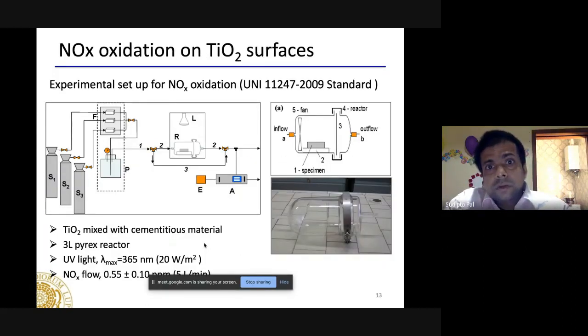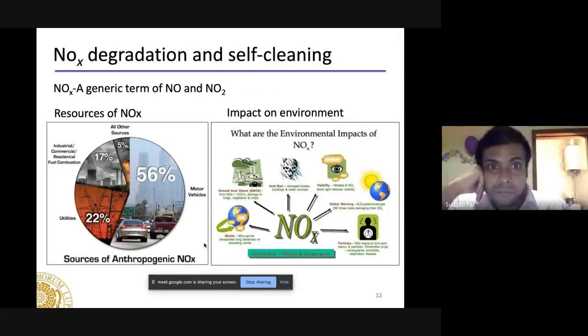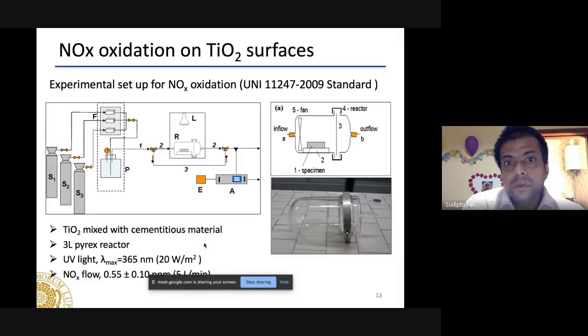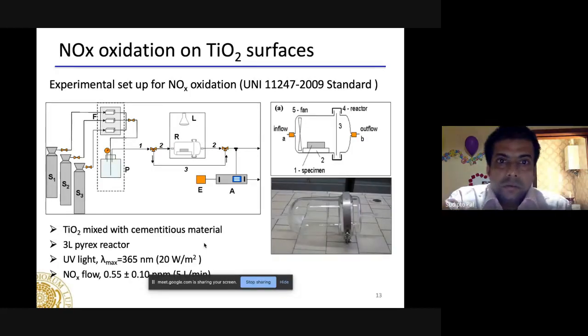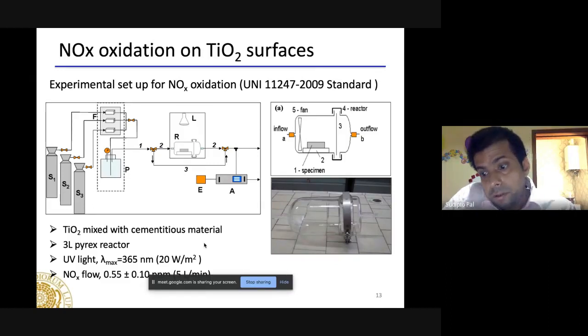And here I will show a setup where, at laboratory scale, we can check with the use of a photocatalyst whether it is working to degrade the NOx or not. In the first slide, you can see NOx is a combination of nitrogen oxide and nitrogen dioxide. So in this setup, usually we feed from cylinders of NO2 and NO, in combination with air, into this glass vessel, and with the gas chromatograph we can monitor whether it degrades or not. With this setup, we can see whether a photocatalyst is working to degrade the NOx.